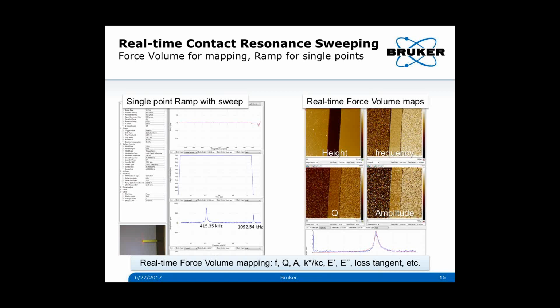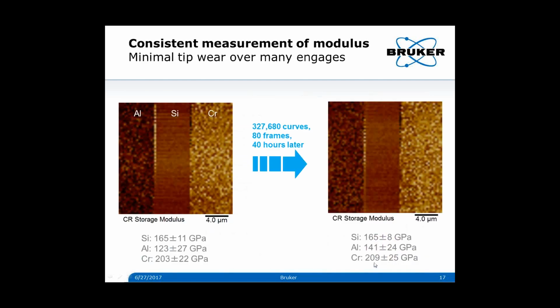When we're setting up, we typically use the single point measurements on the left here, where we do a force curve with a sweep. Here we're showing 2 eigenmodes, and then we switch over into force volume, and we do mapping. Basically, at every pixel in the map, it does the force curve and the sweep, and then it does real-time calculations of things like frequency, Q, amplitude. You can get contact stiffness, storage and loss modulus, loss tangent, etc.